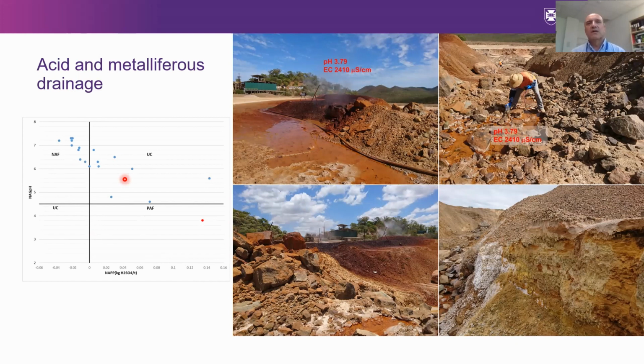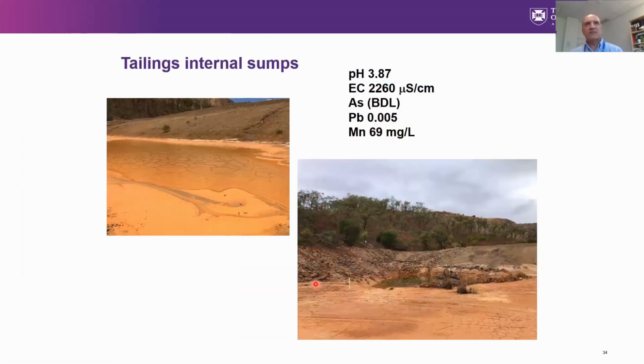It's really more related to this well-sorted material here that is dumped here, and water is sprayed on top of it. They're trying to get rid of the water coming from the water dam, just trying to reduce the level of water there, so they're spraying and evaporating water there. So it's important to understand. But the other interesting aspect that Zhengdong is working on, under supervision by Gordon Southam, is looking at the bacteria. As I said, this shows that the sumps inside the tailings storage facility have low pH, but that low pH is because the water is going through the rejects and is not being neutralized, as there is not neutralizing capacity in the system, in the tailings.